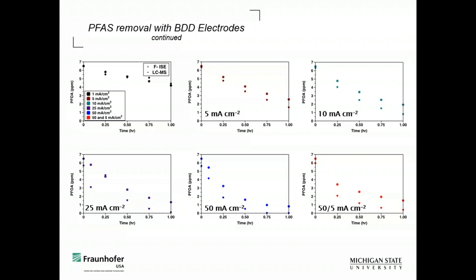And so as you can see, once we get down into 25, 50, there's no PFOA remaining. But as you can see, by the ISE, there is some PFOA remaining. So that's where we thought for the first time, okay, we're probably generating some short chains. And then at the same time, we also verified this with our 50 and 5. And again, if we run this for another half hour, we get down to where we need to with 50.